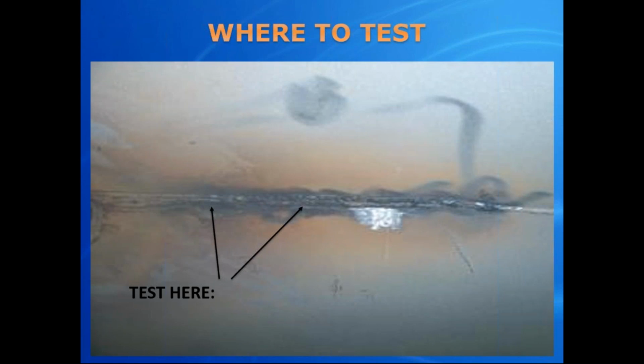on either side. Ladies and gentlemen, you've seen over the years where a coating system fails all the time. And you know, I always brag about paint. It's not that smart. Why do you blast something, say a tank, for example, and it looks extremely well, but it starts failing at the weld seams alone, when it's the same applicator, same blaster, same atmospheric conditions, same coating, same batch, and everything applied at the same time, and then it fails at the weld seams. If you see failure at weld seams, always go and test at those weld seams. And basically all you need to do there is check for chlorides, and I can promise you that you're going to find salts there. You're going to find the chloride salts there, and we did some investigation as to why.